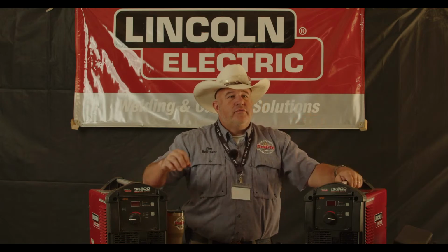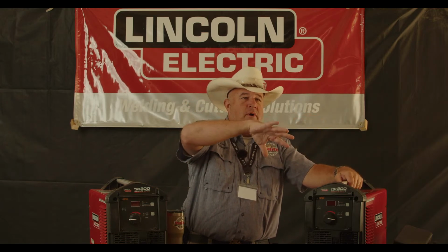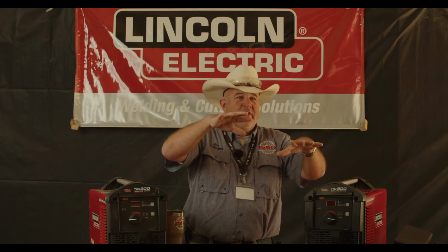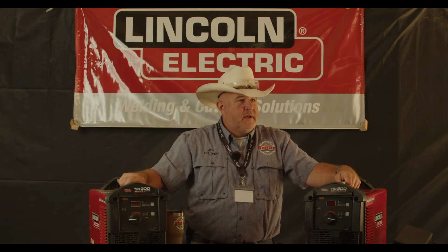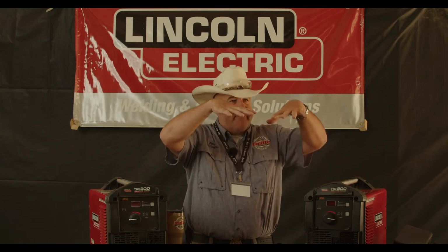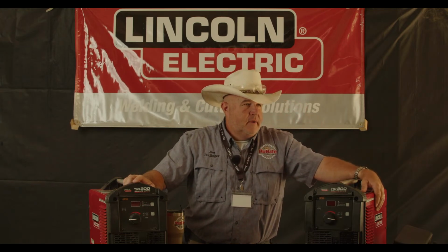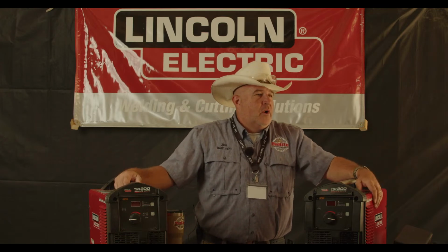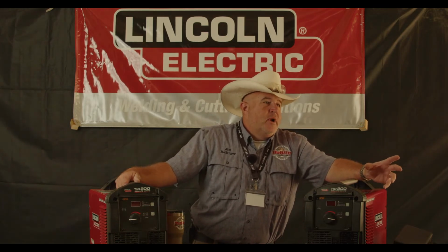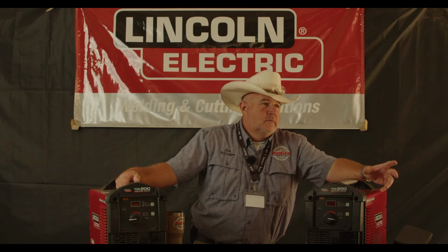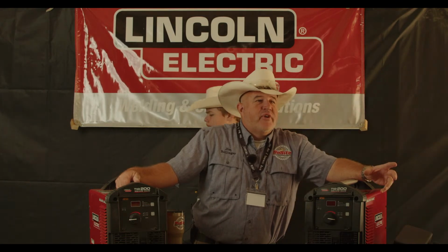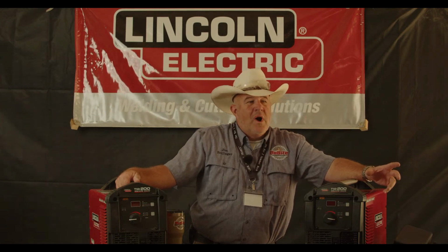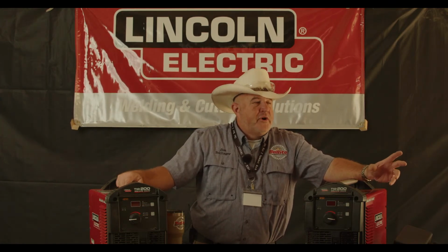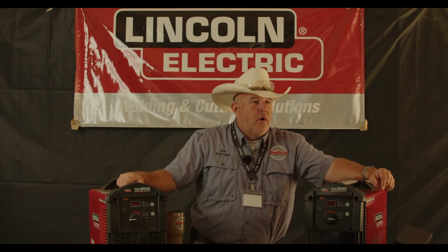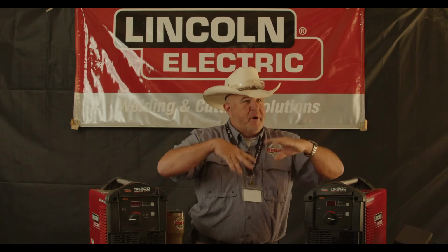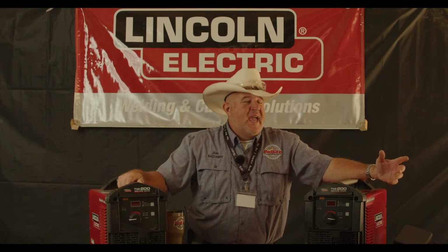When you did that, did you notice that there was like a crust on top of the aluminum? It looked like a pie crust floating on the top of the puddle. That pie crust, the thing that's floating on the top, is the aluminum oxide. At 1,200 degrees, roughly, depending on what you're welding, that aluminum melted. You didn't get to 3,600 degrees to melt the aluminum oxide. Do you know why? Because at 3,600 degrees, the aluminum would have already started to boil, and it would start popping. Pop, pop. And you can't get it hot enough to get it off.